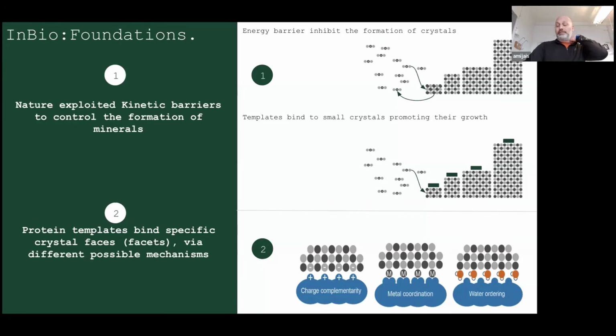If you're able to specifically target a facet of this tiny nanoparticle and bind it, then you stabilize it by lowering the energy needed to form, and it will continue and form a particle that is also related to the facet you're binding. Based on these basic principles, we came up with 3 assumptions on how to target our semiconductor material. The first one was maybe even naive: if the surface is positive, we would do a negative protein, and if we do it in the right periodicity, they will just match.